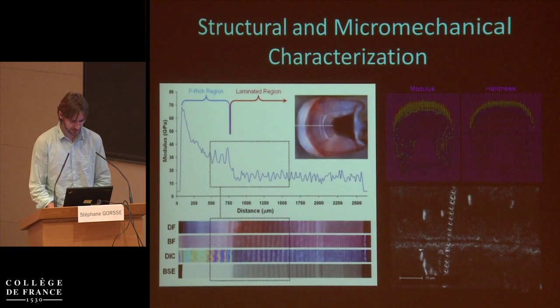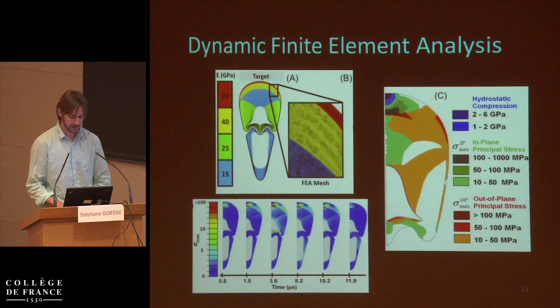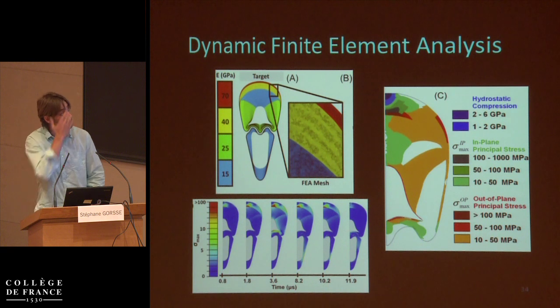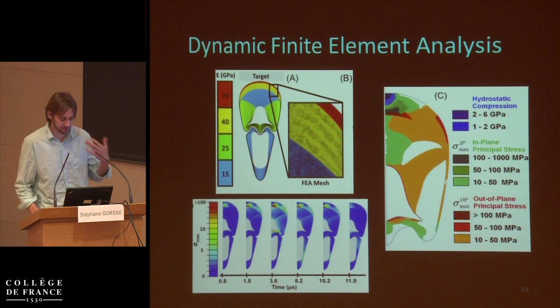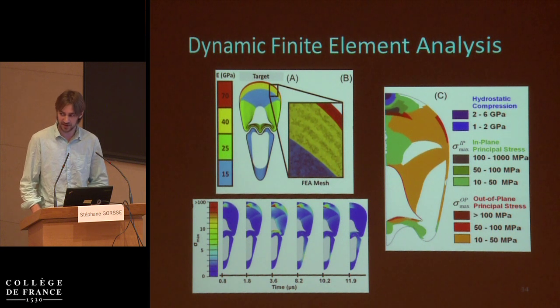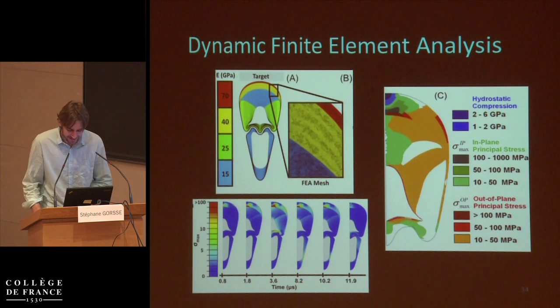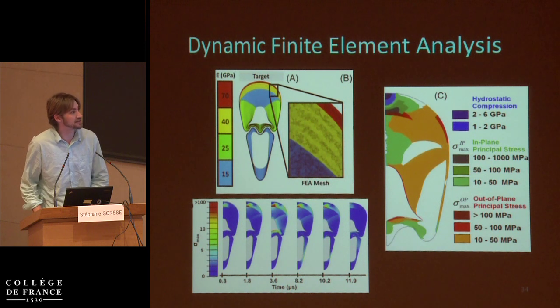And so if we look at the nanoindentation line scan down the center, you can see again confirming that it's very, very hard at the impact surface and then graded, and then it follows an abrupt modulus mismatch, and then you have a periodic modulus. And if we plug all these values from the map into a dynamic finite element analysis and then impact it with a force and velocity comparable to what you'd expect from the actual organic situation, then you get a hydrostatic compression upwards of 6 gigapascals, which some of you may know exceeds the strength of zirconia.